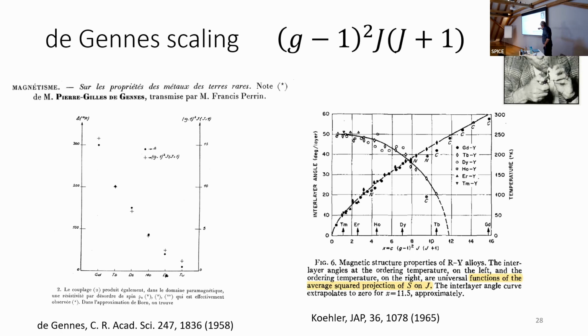So here we have the Curie temperature as a function of, and here we have this de Gennes factor. Here we have the de Gennes factor on the x-axis, and here we have the interlayer rotation angle in all sorts of alloys of these materials. Here we have, again, the ordering temperature, and it all points to say that the magnetic coupling should also scale with this quantity, which has also been shown in theory. I went through lots of papers in French from the 1960s. This was not easy because my French is not very good. But it turns out that that is really what we want to expect here.